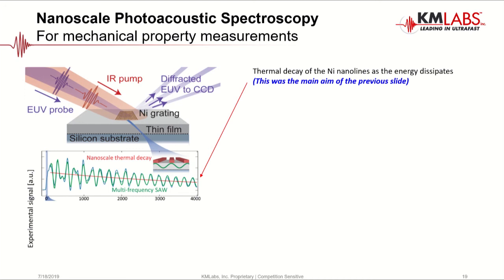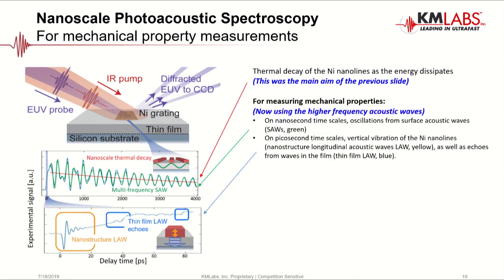And so we can follow a similar type of pump probe arrangement. And what's shown here on this graph is a similar type of vibrational behavior and decay back down to equilibrium. So this is kind of a similar type of effect that we saw previously. But if we zoom in at the very early stages of this process, the first few picoseconds, which is what's shown by this highlighted blue region to the far left of that plot there, we get some other characteristic vibrations that happen very rapidly and very early on in the process.